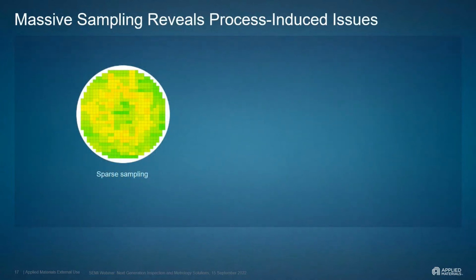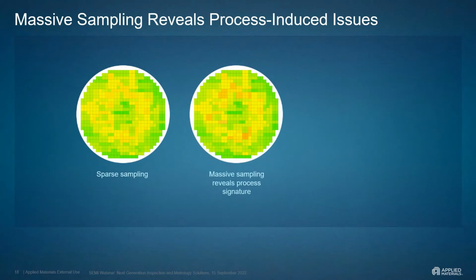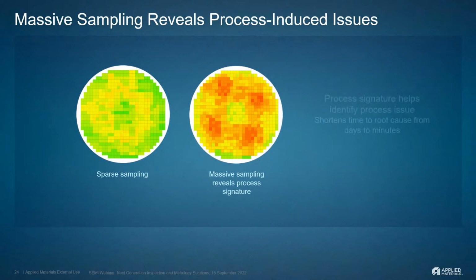And here's a beautiful example. Here's a sparse sampling of some parameter across the wafer. And here we see more massive sampling, which reveals some kind of signature. And the more sampling that we apply, you can see eventually a true signature, which helps to identify a process issue, and this shortens time to root cause from days to minutes. So it's really important to have massive sampling to reveal process-induced issues.